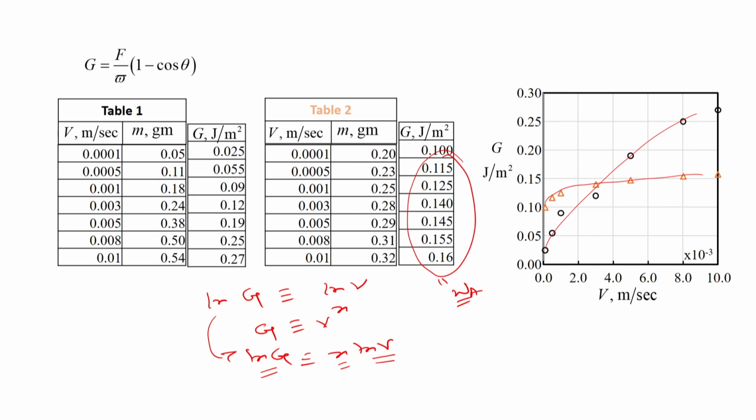Normally, if the substrate has got Van der Waals type of interaction, then there is very low possibility of rate dependence. On the other hand, if there are hydrogen bonding and other functionalities, then this rate dependence might increase. So, these are the various things we can say about these results that we presented here.